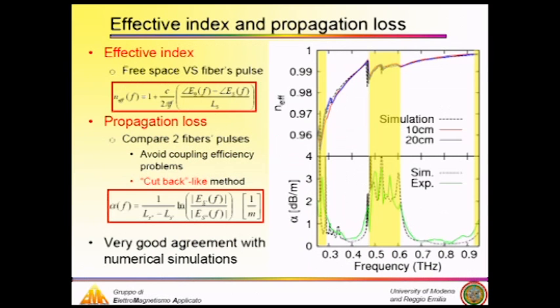So these are the formulas that I've used to compute the effective index of the fundamental core mode and the absorption loss. In the first case, I have compared the free space propagating pulse with the one that's propagating inside the hollow core fiber. Whereas in the second case, I've compared the pulses propagating inside fibers of different lengths, and this allowed me to avoid coupling efficiency calculation, like in the very classic cutback measurement for infrared or other kind of classical waveguides.